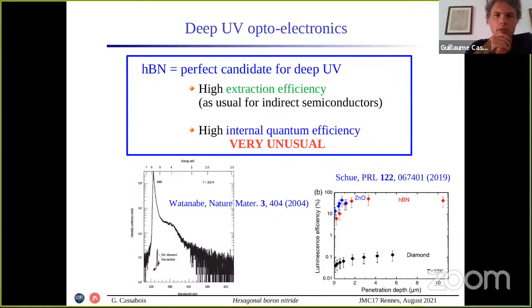More generally, HBN appears as a perfect candidate for deep ultraviolet optoelectronics. It has a high extraction efficiency, which is usual for indirect semiconductors. High extraction efficiency means that absorption and emission do not occur at the same energy or wavelength, due to the fact that they are assisted by phonons. So there is a natural separation, a splitting of the absorption and emission response, and this is very usual in indirect semiconductors. What is extremely unusual is the fact that we have a high internal quantum efficiency, which is usually the case in direct semiconductors.